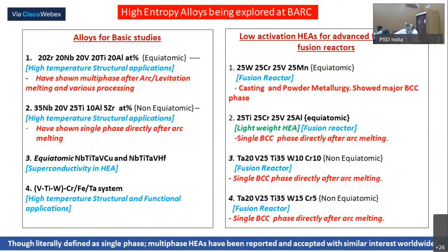Why superconductivity? Superconductivity is basically how you can quickly form the Cooper pair, which remains stable to the highest temperature. That gives you very good superconductivity. Now, as I was telling you, each unit cell has its own composition and they have a lot of strain among themselves. So the Fermi surface will disintegrate because the Fermi surface cannot maintain integrity across the different unit cells. So it will form a Fermi band, and because of the lot of room available, electrons may have a chance to form the superconductivity. That is the idea of exploring this.